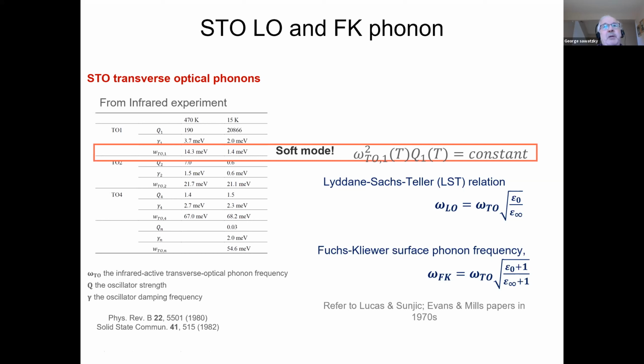However, there is no temperature dependence actually seen in the photoemission or in the intensity of the electron energy loss spectrum. And that's because there's a rule that omega squared times Q is a constant. Okay, so we get rid of that first. So this is the transverse optical phonon, and you know from the Lyddane-Sachs-Teller relationship that the longitudinal optical phonon is the transverse one times the square root of epsilon naught divided by epsilon infinity. And the Fuchs-Kliewer surface phonon frequency is just the same thing, except you add a 1 because it's a surface effect. The vacuum has a dielectric constant of 1: epsilon naught plus 1, and epsilon infinity plus 1.